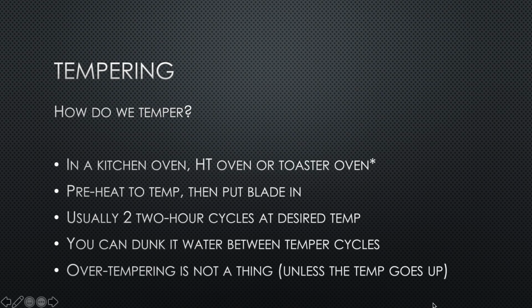Make sure you preheat to temp before you put your blade in, because especially in a toaster oven, you've got that burner right underneath that's cranking full blast. It's probably going to go over your temp. And usually everyone will recommend two-hour cycles at whatever temp you want.